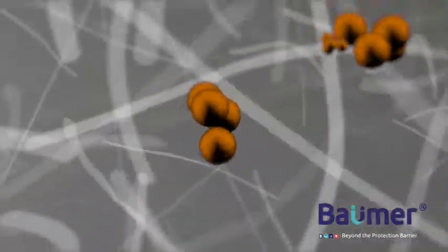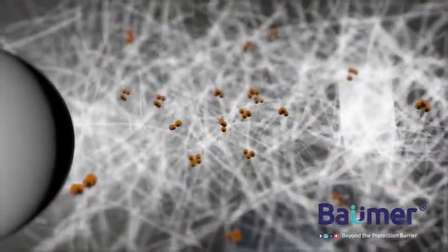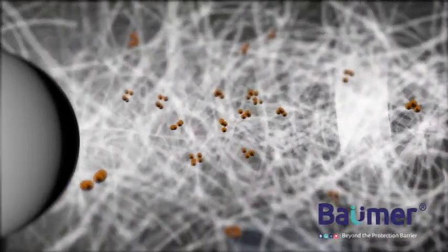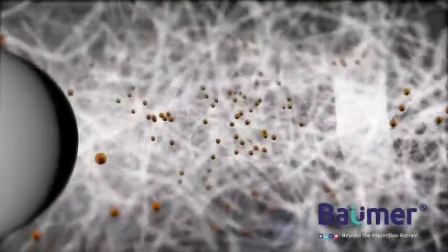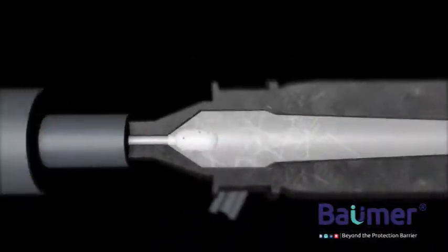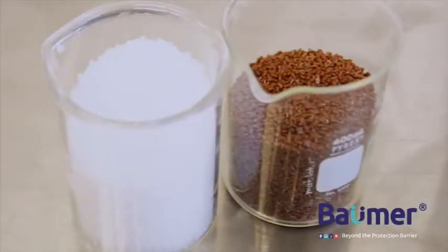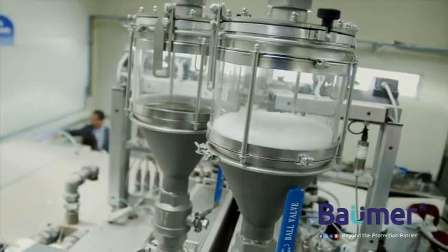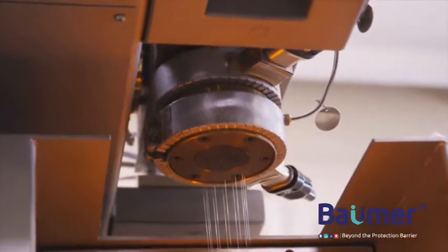To introduce the nanoparticles, we use specialized machinery with a double extruder, in which the resin is incorporated in a pellet way. Inside the extruder, with the help of heat, the pellet melts, and with the application of shear forces, the nanoparticles are incorporated and mixed inside the polymer by an ultrasound-assisted extrusion.